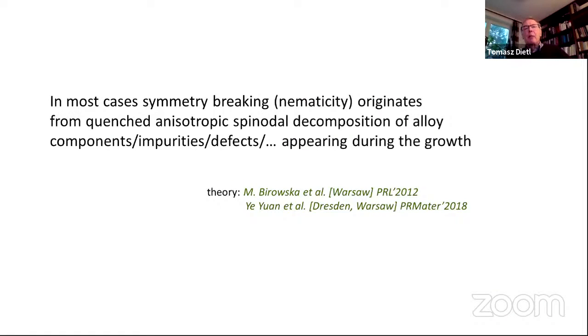What our results suggest, and we see there are more arguments towards that, is that in most cases, not in all, this symmetry breaking, this nematicity which people discuss, originates from quenched anisotropic spinodal decomposition of alloy components, impurities, defects, which appears during the growth, not due to spontaneous formation of a many-body phase, for instance, due to charge ordering. So one should be very careful, and you can ask about the physics: what causes this anisotropic spinodal decomposition?